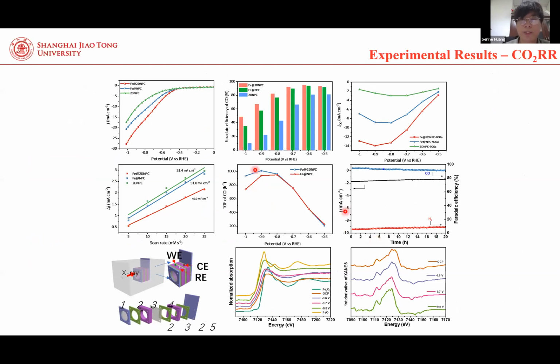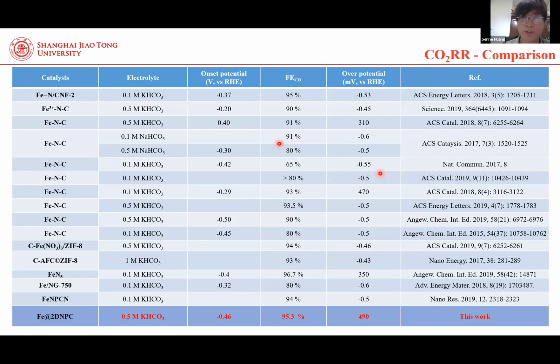The experimental carbon dioxide reduction reaction testing also shows the as-prepared catalyst exhibits promising carbon dioxide reduction reaction catalytic performance. The operando X-ray absorption spectroscopy indicates ferric iron is a significant active site for carbon dioxide reduction reaction. After reduction to the ferrous iron, the activity and the selectivity of the catalyst decrease. The above description is also consistent with the Bader charge analysis. The catalyst has a maximum Faradaic efficiency of CO of 95%. This high selectivity surpasses most of iron-based catalysts for carbon dioxide reduction reaction.